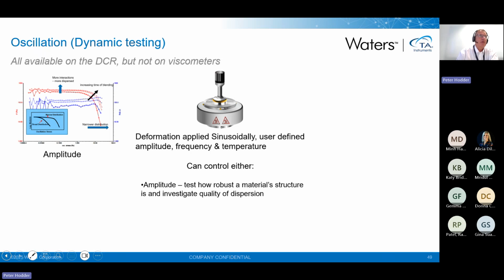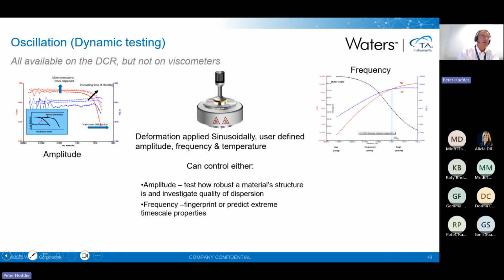And here's an example, showing that you keep taking samples at periodic mixing points. You can see that the value of this plateau, that red line, starts to go up and then plateaus off at a constant value. You've made a final dispersion. With frequency, we can see a sample fingerprint, but we can also predict extreme timescale performances like long timescale creeps. So like a pressure sensitive adhesive on a post-it note, how long will it stay up? Or stability, or a simulation of maybe a car wheel going over something.